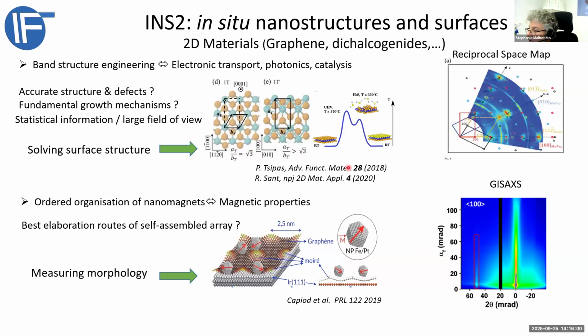Two examples just to illustrate that you can perform such a beautiful reciprocal space map of the not so many layers of atoms on top of a substrate, and you can have the signal from the substrate, from the different layers. Then by fitting the intensity, you can deduce the atomic structure. You can precisely measure the distances between all the atoms by least square fitting of a model with ROD, the famous ROD analysis software.